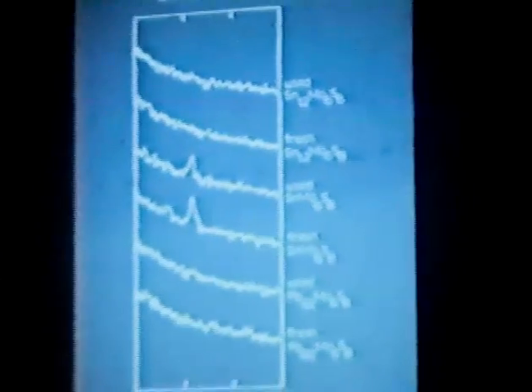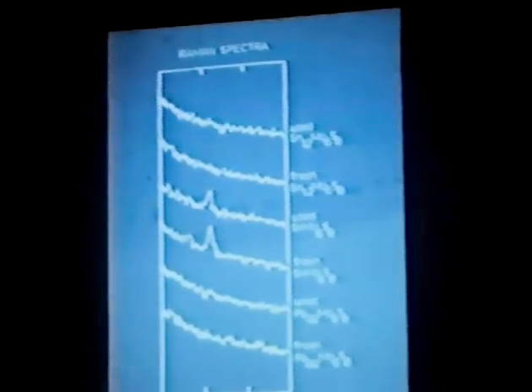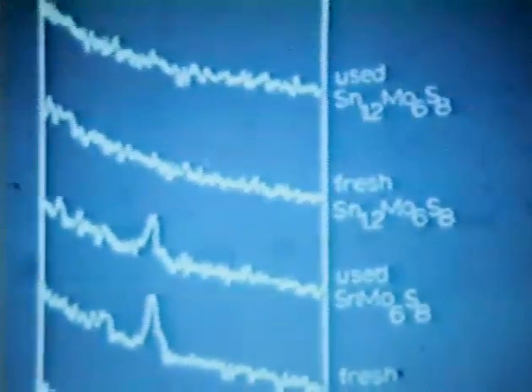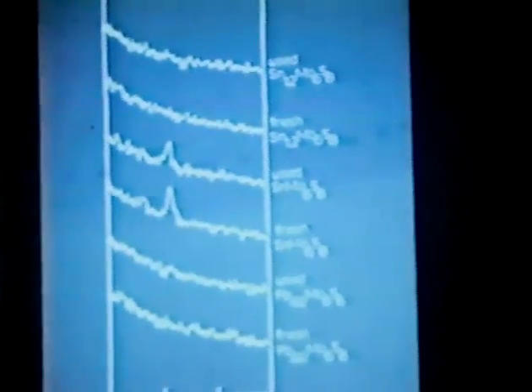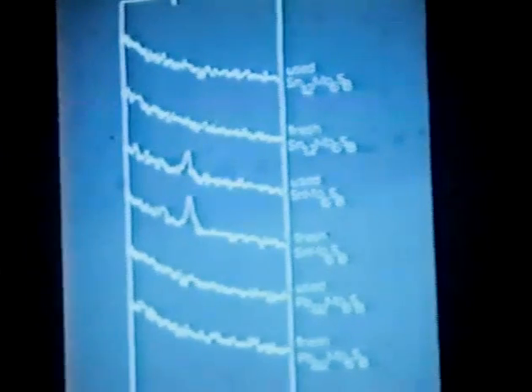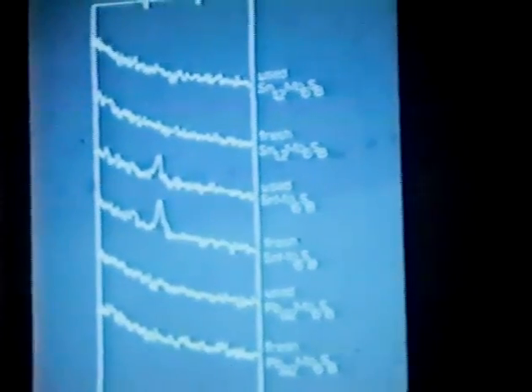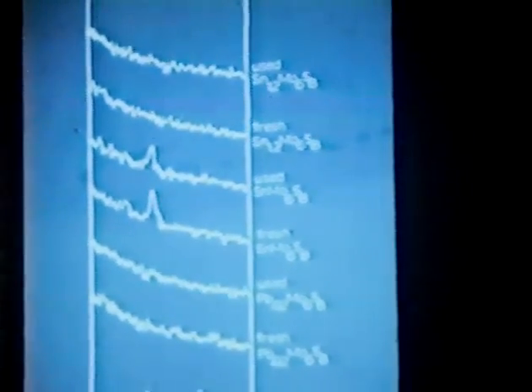With X-ray diffraction, we were never able to see any crystalline MoS2 in any of the compounds. Using laser Raman spectroscopy, we searched for any type of amorphous or non-crystalline MoS2, and of course using the Raman technique, you can find poorly crystalline MoS2 very well. And in fact, we never saw any poorly crystalline MoS2 except for 2 compounds in the fresh tin Chevrel phase compounds and the used tin Chevrel phase compounds. You can see some MoS2. And the cobalt Chevrel phase compounds also produced some MoS2 in the used catalyst, although the initial catalyst did not have any MoS2 present in there.